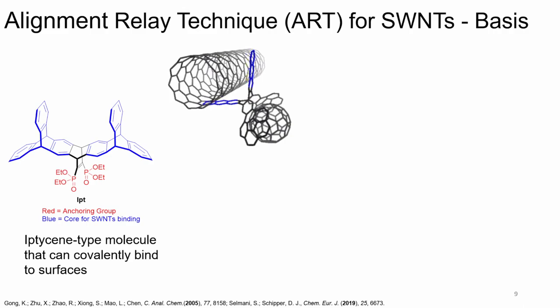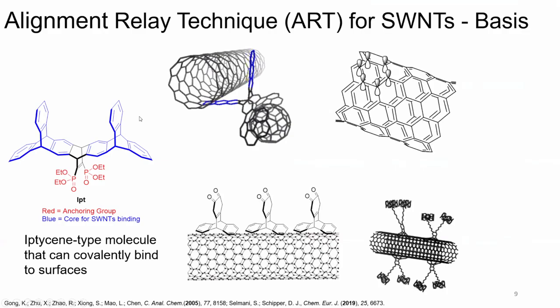Now, this method is based on iptycene small molecules, which have been shown to have pi-pi stacking interactions with carbon nanotubes. And that is because of their favorable double bond sp2 backbone. And that's found in both systems. And the pi bonds themselves, so those double bonds that create these benzene ring systems, they favorably stack to one another. And that's common throughout the literature.